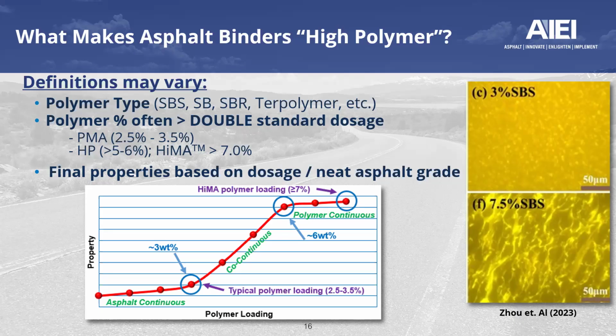The final properties of your blend between your base binder and your polymer are highly dependent on the polymer content itself. In the graph that we have, at a lower polymer loading, we see an asphalt continuous behavior of the final blend. When we're pushing beyond 3%, we start seeing co-continuous behavior between the base asphalt and the polymer. And we see more of a polymer continuous behavior when we start pushing these high polymer content levels above 6%.